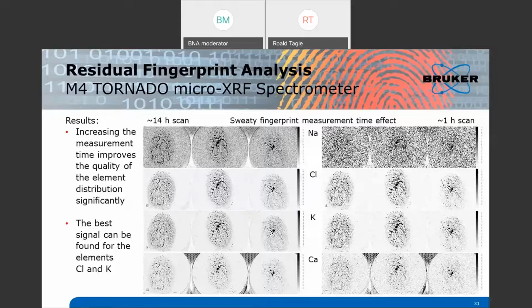Here we did a longer measurement time, so this is an overnight scan of the same sample that was previously measured for one hour. And what you see here is that we improved the contrast. Since now we have better statistics, we start seeing some fingerprint for sodium, and we have considerably improved the result for potassium and chlorine, and also for calcium.